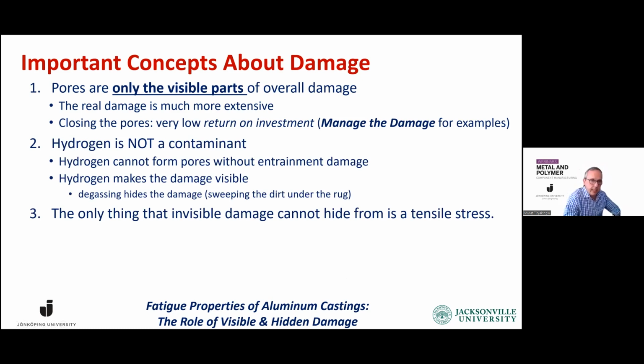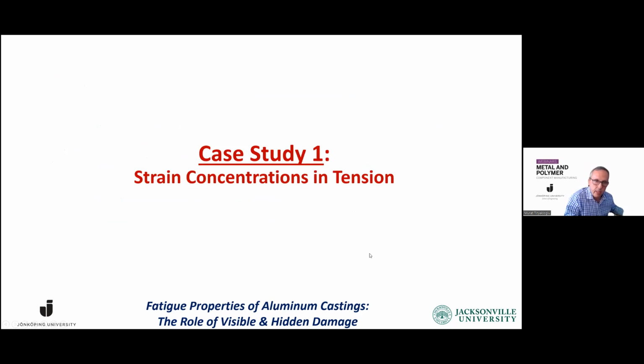We are of the opinion that hydrogen is not a contaminant. Hydrogen cannot form pores without entrainment damage. Hydrogen makes the damage visible, and if you bring the hydrogen level down, all you're doing is hiding the damage. You're not making the metal better, you're just making the damage invisible. And the only thing that the invisible damage cannot hide from is a tensile stress. With this, we jump into case study one.